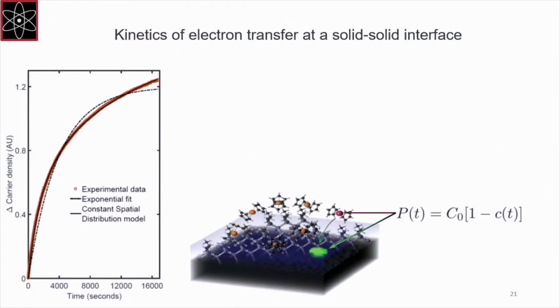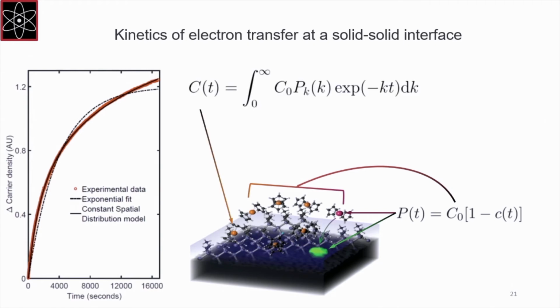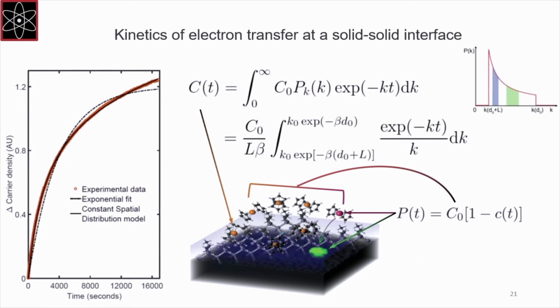So we developed a model based on the simple idea of a continuous distribution of rates, and the result was quite in agreement with the data. So what does the model entail? The curve here is basically the evolution of the population of electrons as a function of time. And that's given by a factor C0, the total population that's electron transfer active on your surface, times 1 minus the fraction that's still able to react. And that thing decays exponentially, but weighted by the reaction rates of that particular distance. And that's just to let people know what equation was used in this curve. And there's only actually 2 fitting parameters, the same number as a simple exponential fit.